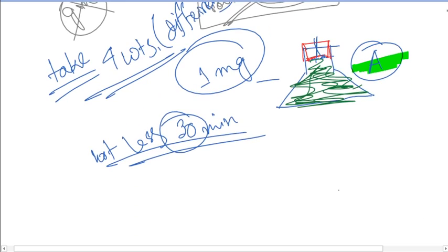The water bath is always kept at our expected test temperature, which will be 25 degrees centigrade or 15.6 degrees centigrade, whatever we are using. So we ensure that the picnometer, including the water and everything, maintains the actual test temperature. Whenever 30 minutes is over, we remove the picnometer,